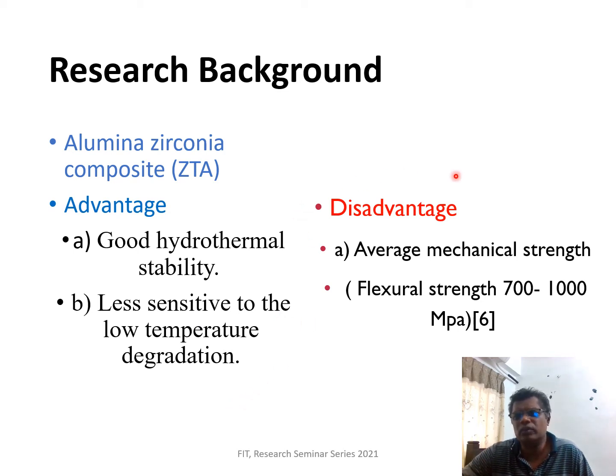But it also has a disadvantage. The mechanical strength of the alumina zirconia composite is found to be 700 to 1000 megapascal, which is average. Y3 zirconia is able to achieve up to 2200 megapascal, so quite good mechanical strength. So although alumina has good low temperature degradation resistance, it has, not poor, average mechanical strength. So it can break easily relative to Y3 zirconia.